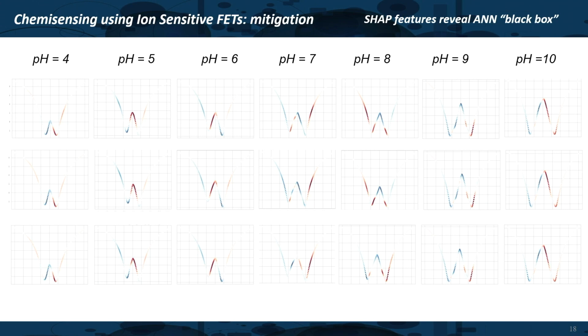And what we found is that if you compare pH 4, you see that these blue regions are all activated for pH 4, while other regions are activated for different pH values. This means that the network is not looking into a single parameter, but into a part of this IV characteristic in a very subtle manner, because the weight for each of these points is different. And there is no mathematical definition of how to describe a part of these characteristics. This is precisely why the network works so much better, because it looks into very subtle changes in the IV characteristics, which is beyond mathematical description. So we get a very high accuracy because of this interesting aspect.